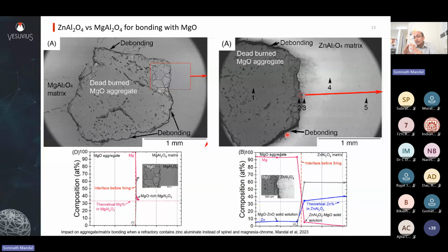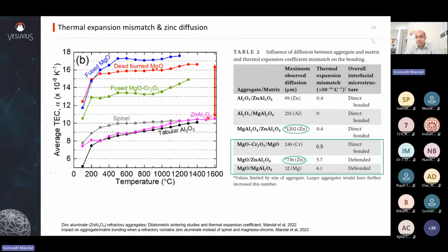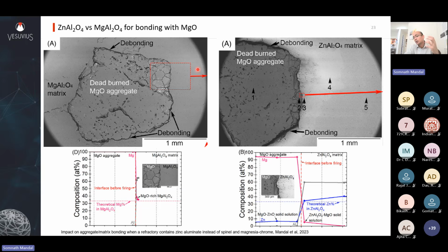From that, instead of having 36% pure zinc aluminate, maybe have 50-50 magnesia and zinc aluminate. So now your expansion coefficient, instead of being here, you are somewhere here. And due to the reduced difference in TEC between your new matrix and the aggregate, you will close up your debonding and you will have a better bonded structure. You don't want zero debonding, because this debonding actually is helpful for good thermal shock resistance. So you need to strike a balance. And that's why a lot of refractory scientists are hired in the industry, because they need people who understand these nuances and develop better products that replace the existing competing product in the market.